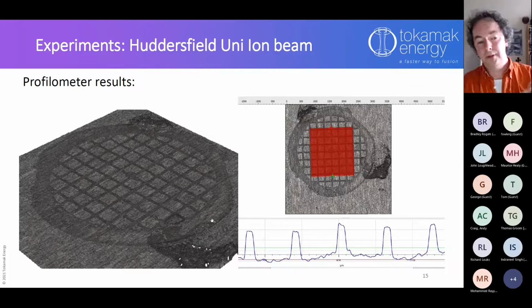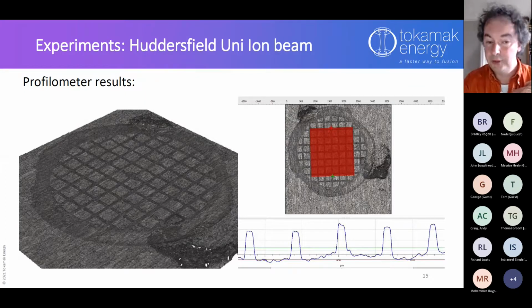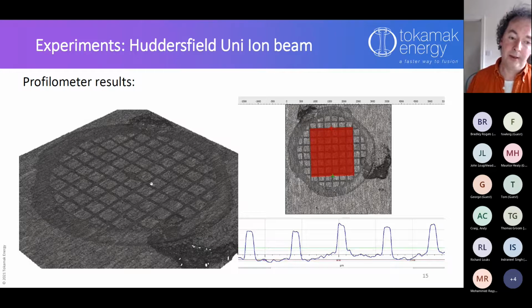We have to expose these for about 3 days, because the reason we're using tungsten is it is pretty resistant to erosion. So to see anything that you can measure, you can't just do a 1-hour experiment because you just don't see anything. But after 3 days you see a pattern like this, and what's happened is the molybdenum grid has been over this part, and these darker lines are where the grid was. They have been protected, and in between each of the grid wires, this section has been eroded.